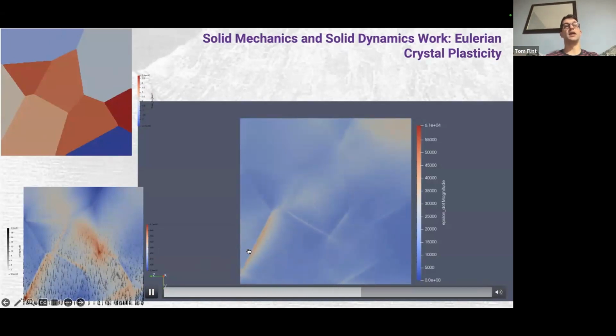So here is, for example, where you would get more plastic deformation in this region here, this band that aligns with this grain boundary. Also, because we fully solve all of the physics, we get local temperature increases due to that localized stress. And the more up-to-date version of the code actually has thermal softening, so we can predict things like adiabatic shear banding. So I guess this work would be of interest to anyone in the metal forming sector.